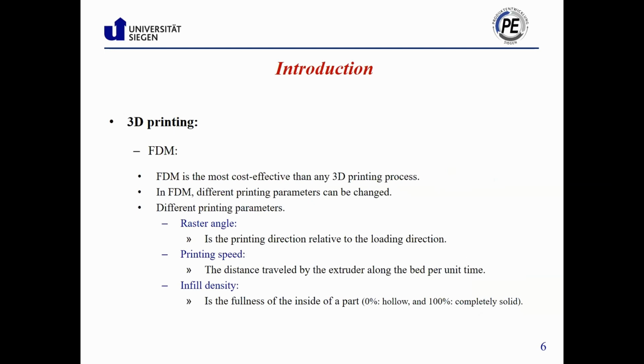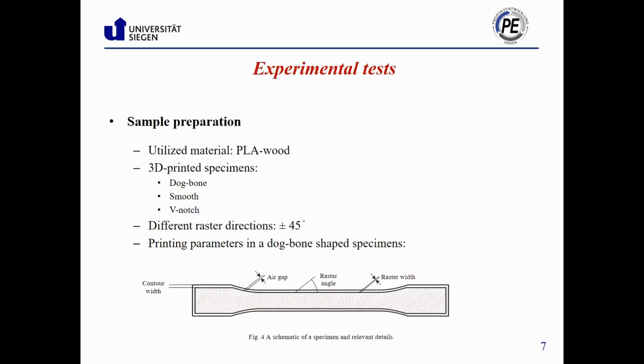In the FDM process, different printing parameters can be defined and changed. For instance, printing speed, layer thickness, nozzle temperature, and air gap can be defined with desired values. In this slide, 3 parameters are listed: raster angle, printing speed, and infill density. For example, printing speed is the distance traveled by the extruder along the bed per unit time. However, it is often difficult to control all printing parameters together. And let's go to the second section, which presents details of the experimental test.